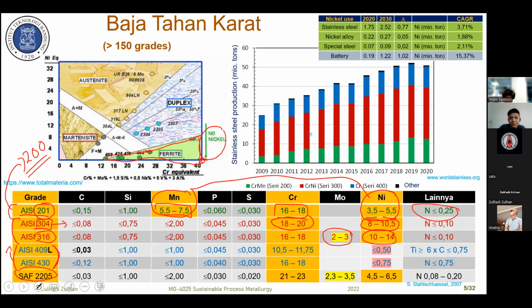If you see the production of these kinds of stainless steel, the 200 series is given here in green color. The nickel content is less than 6% or less than 8% in general, and most of the nickel is substituted by manganese. The most popular stainless steel in the world is the 300 series. This includes 304, the most common. I think this steel grade is produced at more than 30% worldwide. And the last one here is the 400 series. The small portion is the other steel grades, including duplex, precipitation hardening, and other kinds of stainless steel.